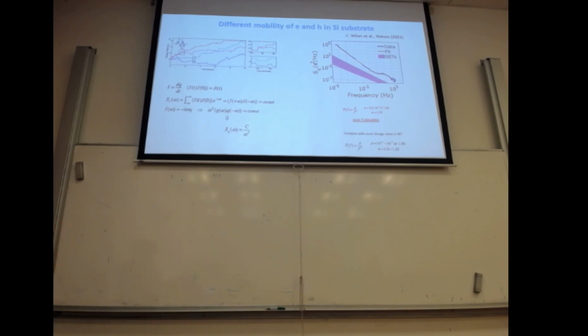Namely, that the charge noise in transmon is very different from the charge noise in SET. And this was somehow very surprising, because when we were talking to Martinis, for example, he said, oh no, charge noise in transmon should be the same, 1/f like the SET, because the mechanism is the same, you have this dipole and so on. Instead, what is found is that the charge noise in transmons, which can be measured because transmons can be built with some configuration of the Josephson junction so that they become sensitive to the charge, is always 1/f squared, and it is bigger.